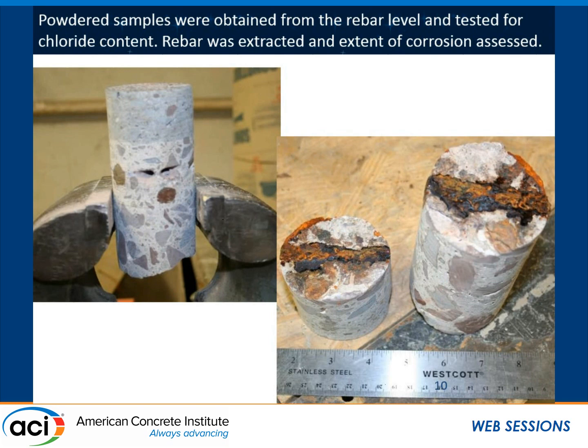Okay, thank you. I just wanted to make a quick comment about one of the first questions, about the possible reasons for the increased cracking density in half-bridge construction. Based on my experience, one of the reasons may be the increased degree of restraint, specifically if you have a bridge deck with half the deck cast and the second half tied to this first half. What I've seen is that a lot of the transverse cracks propagate from that first half and actually taper off towards the edge. Yeah, that's a great comment. The first half would create a lot of restraint on the second half. Okay, thank you.